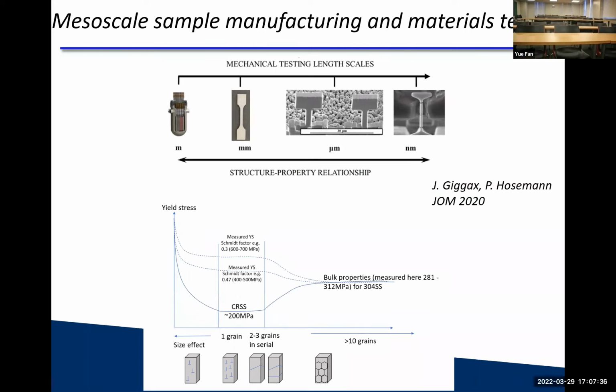And this comes, of course, from the dislocation density changing during your plastic deformation, right? If your sample gets smaller and smaller, at some point you have no space for dislocations to be, and therefore it becomes almost ideal strength. People have shown in whiskers that they get very close to ideal strength. And so it comes down. But then the question is, what's your Schmid factor? If the Schmid factor is different, of course, then you get very different outcomes.